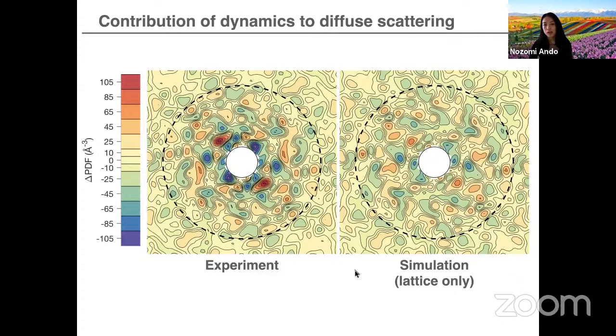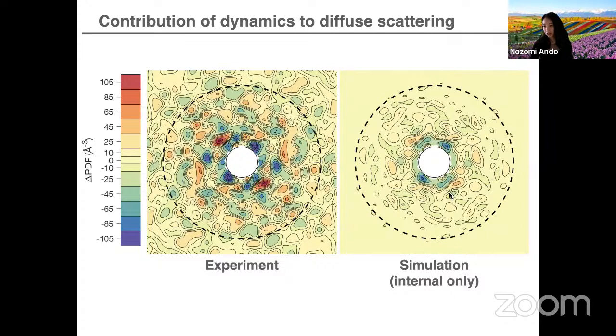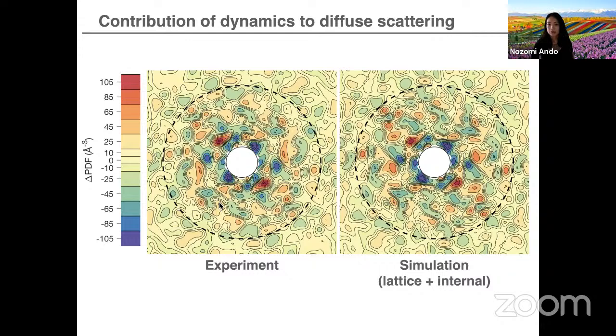On the other hand, if we look at just the internal dynamics model, we only get short range correlations, as we would expect, because they should be the internal correlations of the protein. What was great was that when we added the two, we got remarkable agreement with the experimental diffuse Patterson. This is the best agreement that the field had seen in terms of explaining the contributions to the diffuse scattering signal.